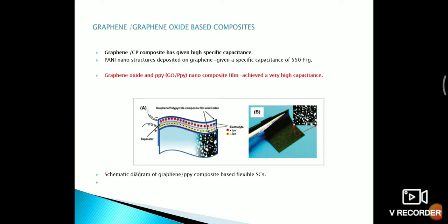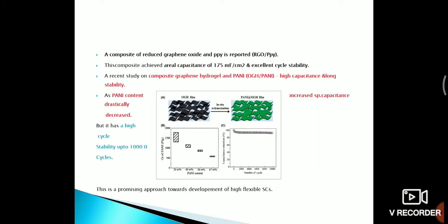Next is graphene or graphene oxide based composites. Graphene or conducting polymer based composites have given high specific capacitance. Polyaniline nanostructures deposited on graphene give a specific capacitance of 550 farad per gram. Graphene oxide and polypyrrole, that is GO-PPY nanocomposite film, achieved a very high capacitance, and this figure shows the graphene polypyrrole composite based flexible supercapacitors. And a composite of reduced graphene oxide and polypyrrole is reported, that is RGO-PPY combination, and this composite achieved areal capacitance of 175 millifarad per centimeter square and excellent cycle stability.